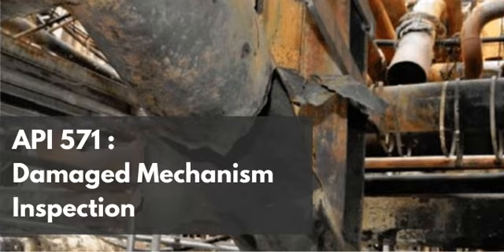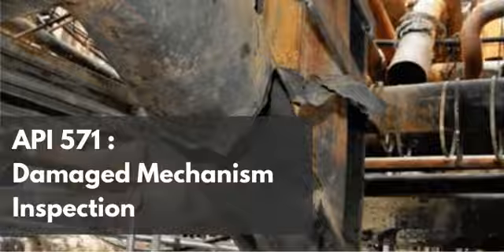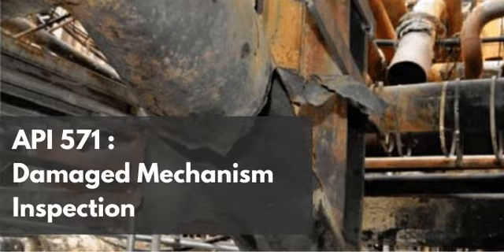Let's start with the front line, contactors and absorbers. Right, the contactors and absorbers are where the lean amine first contacts the sour gas. So you have the chemical transition from lean to rich occurring right there across the fractionator trays or packing. And you have thermal gradients plus massive pressure boundaries. Exactly. If those vessels are constructed of non-PWHT'd carbon steel, the welds supporting the trays and the main seam welds are at very high risk.